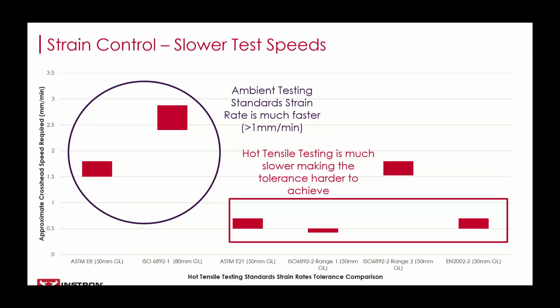On the left, we have two ambient temperature tests, one ASTM E8 and one ISO 6892-1. Their target strain rates are the same, both 0.015 millimeter per millimeter per minute. However, the allowable crosshead speeds are slightly different. You'll notice there's actually a greater tolerance for variation in crosshead speed for the ISO test because the gauge length is larger. Now, when we look at the elevated temperature tests on the right, notice how narrow the window of crosshead speeds is for E21. And it's even smaller for testing to ISO.